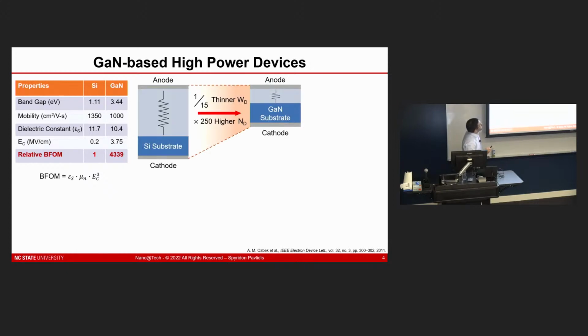More qualitatively, what do we gain? If you look at a unipolar device or a Schottky diode as an example, you go from a conventional silicon device, where the drift region is a low-doped and thick region that has to sustain the electric field. That region can be redesigned in gallium nitride or wide bandgap semiconductors more generally to be thinner and higher doped. That ultimately reduces your drift region resistance, and if that plays a key part in your device's overall loss, it will really reduce the losses in your device as well.